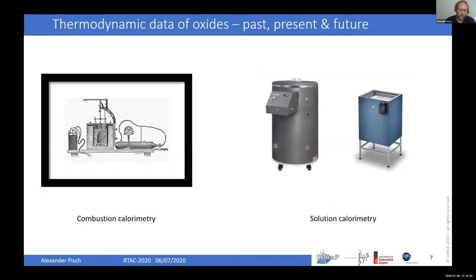So how can we determine experimentally the thermodynamic properties of oxides? Well, this is a very old story and started basically in the 19th century, in parallel with the development of calorimeters. In the case of oxides, basically we have two types of equipment. On the left side, we have a combustion calorimeter, a very old one. There are modern ones also, you can still buy them. The important point is that you react a metal with a certain amount of oxygen and you measure the heat upon reaction. This gives you then the heat of formation of the metal oxide.